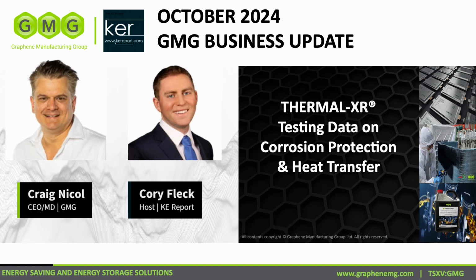Look, this is a huge milestone for the company. 8 years in the making to get to this point, to understand the coating and to be able to test it for this long in third-party laboratories is a really big milestone. The key takeaway is we can now say with confidence that our coating can survive 15,000 hours of continual salt sea spray being dripped on it, which is one of the longest lasting coatings in the world. It's still going. It's not got any corrosion yet, so likely that'll go on for some time. So it's definitely in the top 5 longest lasting coatings, and it's probably going to keep going for some time, as in it doesn't seem to have any sign of any wear and tear so far.